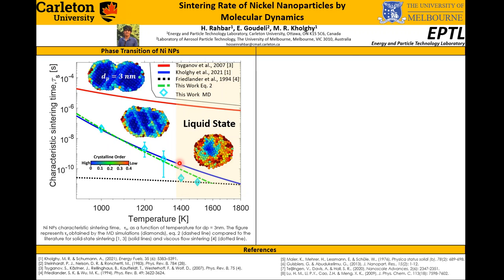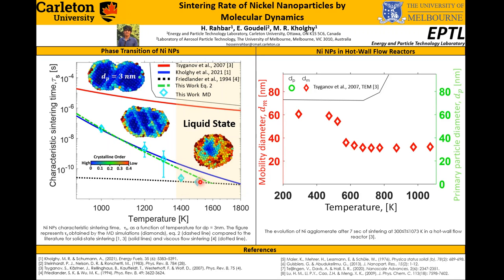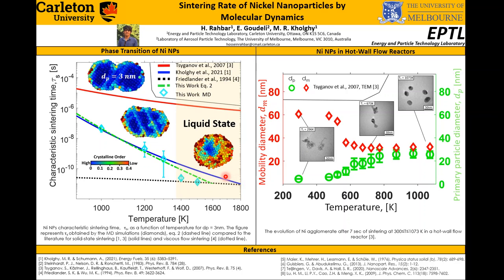Finally, the performance of the MD-derived characteristic sintering time is benchmarked by predicting the morphology of nickel agglomerate in a flow reactor after 7 seconds of sintering. The mobility and primary particle diameter of nickel agglomerate in a reactor are measured by transmission electron microscopy, or TEM measurement, and then compared with the value predicted by molecular dynamics simulations. The results of this study are in a very good agreement with the TEM measurements.